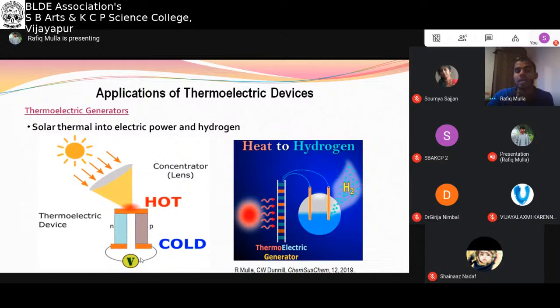and one can get electrical potential. This electrical potential can be given to water splitting units where hydrogen can be produced. By immersing just 2 electrodes in a water bath with some salt, one can produce hydrogen without any problems. The only thing is we need electrical potential or electrical energy, DC current. So that can be achieved by this concept.